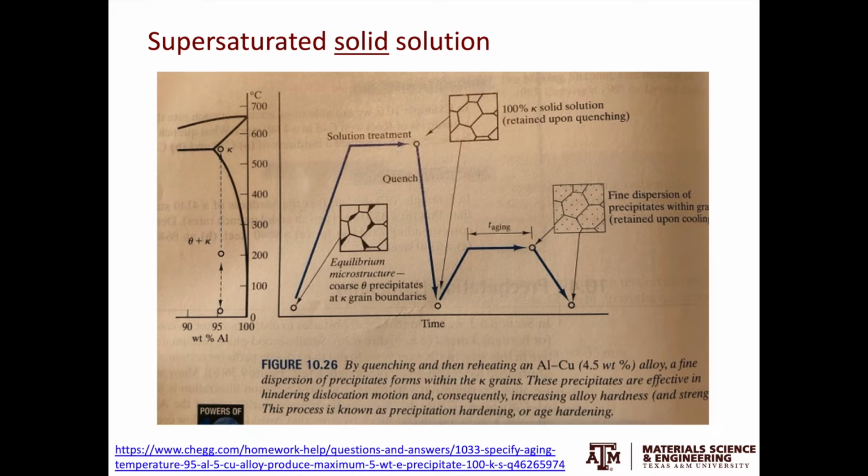Before moving on, I'd like to make a few quick notes here. The first is the process you start by doing solution treatment, then aging to bring out precipitates is commonly used in a wide variety of alloys, including steels, aluminum alloys, magnesium alloys, nickel-based superalloys. So this method is universal. The second thing is when you think about alloy design, precipitate strengthening actually is the most effective strengthening method to make a metal stronger. So this approach has very broad engineering applications.